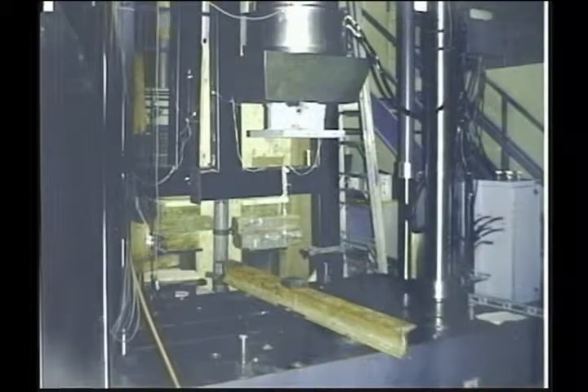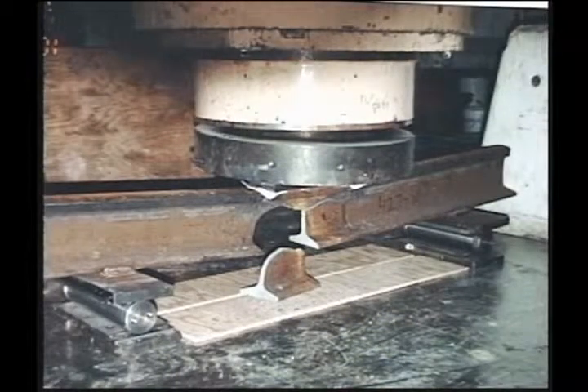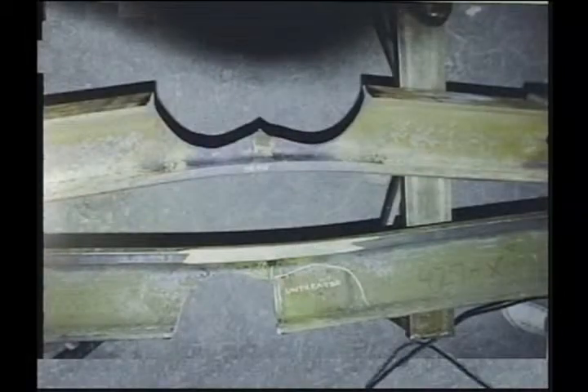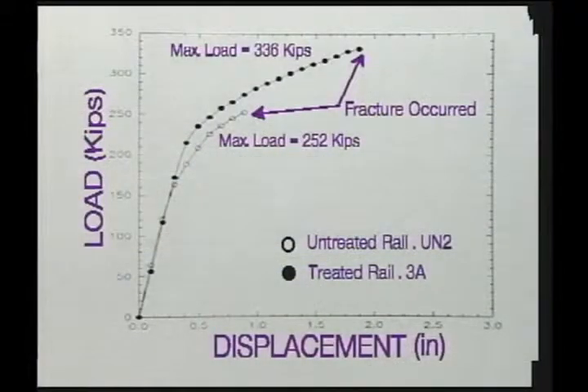In slow bend tests performed at the Civil Engineering Department of the University of Toronto, the load versus deflection curves indicate that the treated welds exhibit significantly higher strength and ductility over the untreated weld. The 4-point bend tests show an increase in load carrying capacity after heat treatment of 33% and an increase in ductility of 126%. This marked increase in ductility of the material indicates a major rejuvenation of the fatigue state of the used rail.